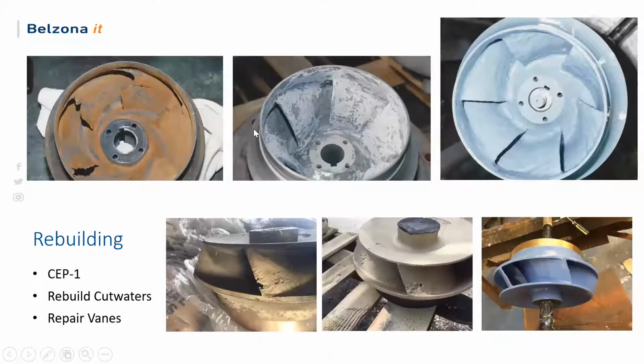This is very typical, we get these impellers a lot at the shop. As you can see here, the vanes are quite beat up. These are a little bit worse on top. The ones on the bottom is a lot of times what we'll see, where they just have pretty good pitting, almost like through wall, through the vanes, and pretty bad pitting at the welds. So what we'll do is we'll fill in all that with the paste grade material. It's 100% solid. When it dries, it's kind of like metal, and you do little staples on all the edges before. So this is an example of after the rebuild.